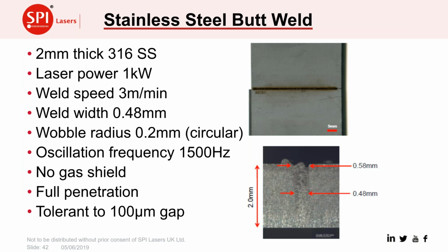And again, we've been able to do butt welding with stainless steel, and you can see just there a little bit of undercut on the top surface, but a good weld. Here we wanted a deep weld, not particularly wide, but we've managed to produce quite a deep weld through the two bits of material that are butted together. Slightly brown on the top, that's because no shield gas was used in this situation. If we used some argon, we would have got a much cleaner looking top bead for the weld.